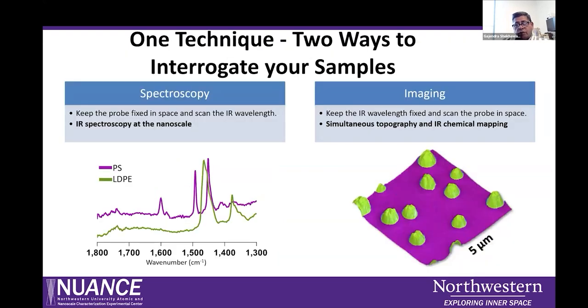It's one technique, but there are two ways you can investigate your sample. One of them is spectroscopy, where you keep the probe fixed in space and scan the IR wavelength. Then multiple samples, or multiple variations in the samples, can be investigated at once. Another option is you keep the IR wavelength fixed and then scan the sample. So you can do the chemical mapping. That mapping you can also do at high resolution, but it can be done only at a very specific wavenumber.